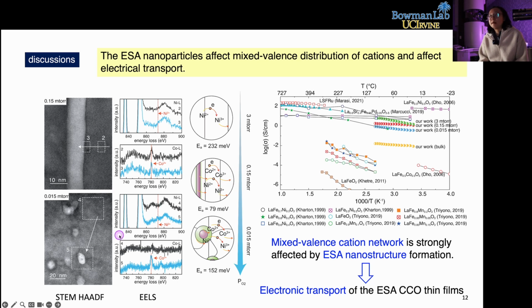At 0.015 millitorr, we can see both cobalt and nickel show valence change around these core-shell nanoparticles compared with the bulk region. So the distribution of these particles also affects cobalt-nickel valence change, or their mixed valence distribution, which has an effect on the activation energy of hopping, and also the conductivity.